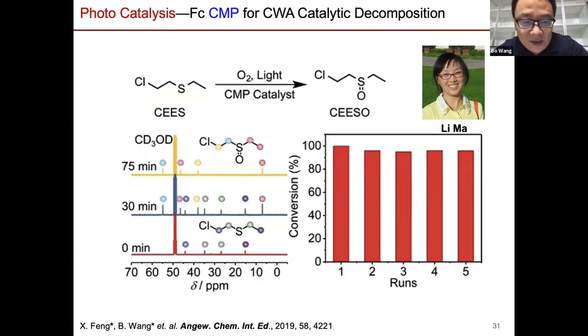Can we further oxidize some warfare agent? In this case, it's CEES. It's very close to mustard gas. Can we oxidize that to the less toxic CEESO? In this case, it's sulfoxide. Instead of oxidizing all the way to sulfone, we oxidize the structure to CEESO. Under visible light, using the CMP we just mentioned, the ferrocene, eventually you can decompose them nicely.